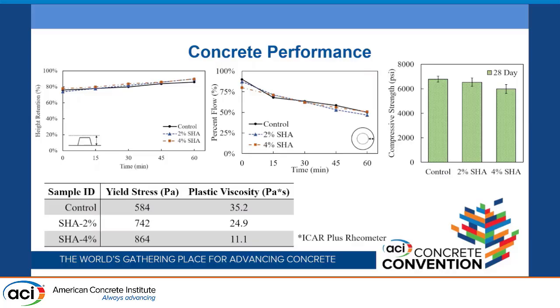We're around that throughout. And then for the flow table test, when you're actually agitating the sample, typically in literature we see in excess of 50% being acceptable. Again, we're ahead of that, up to 75%. Importantly, all of our samples were grouped together, indicating that we're having comparable rheological performance.